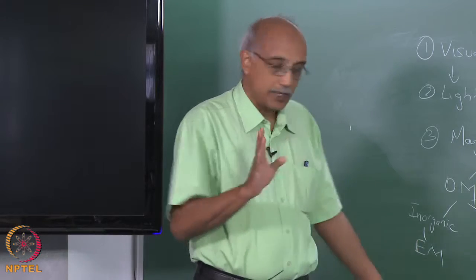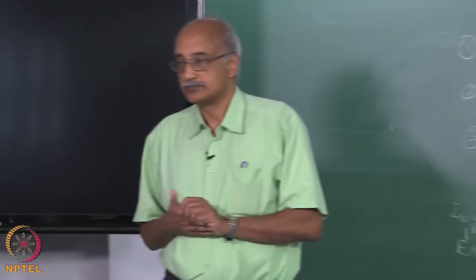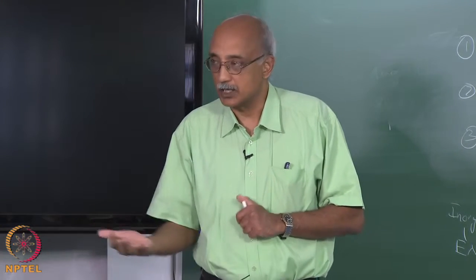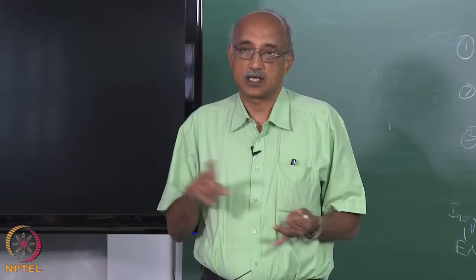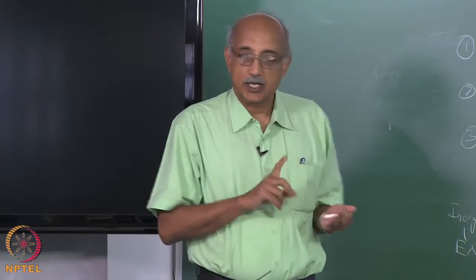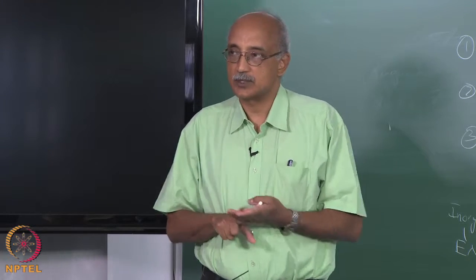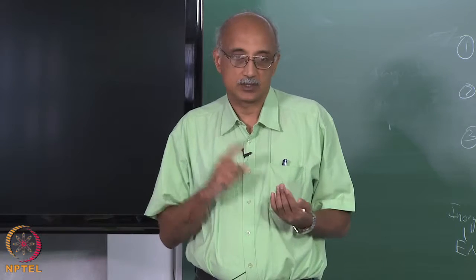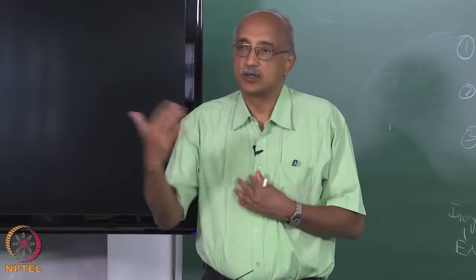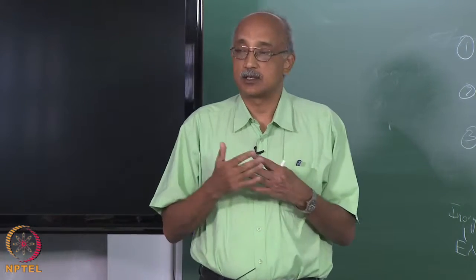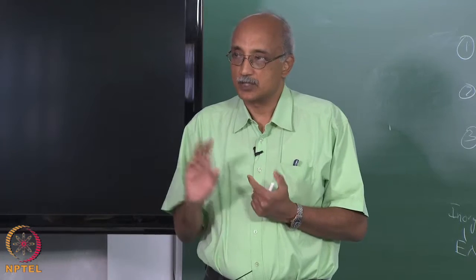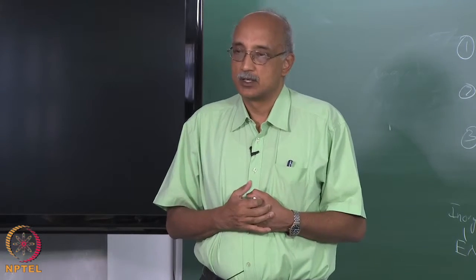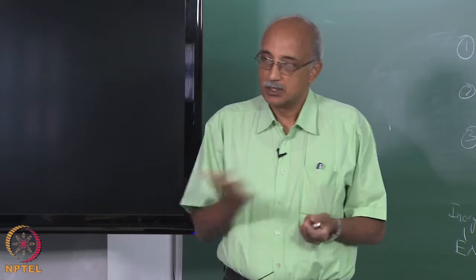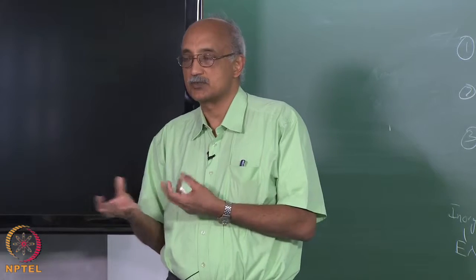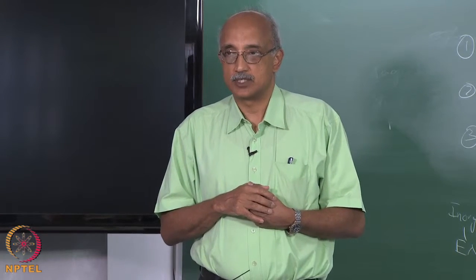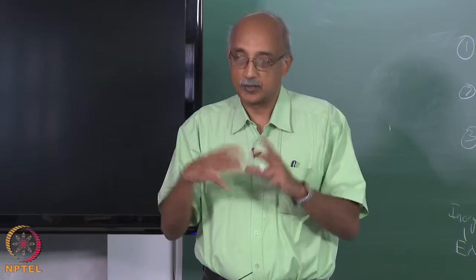So, let us say that it is inorganic and you have decided you need to do electron microscopy. Then again, there is a bunch of choices you have to make. There is scanning electron microscopy, there is transmission electron microscopy, there is Auger electron spectroscopy, there is secondary ion mass spectrometry, there is time of flight SIMS, there's a whole list of things that you could do. Or you could do simple solvent extraction and do chromatography. For example, if the inorganics are primarily ionic in nature, you would take deionized water, measure its conductivity, and then extract the ions from the surface and measure the change in conductivity of the deionized water, and that will tell you how much total ionic material there is on the surface.